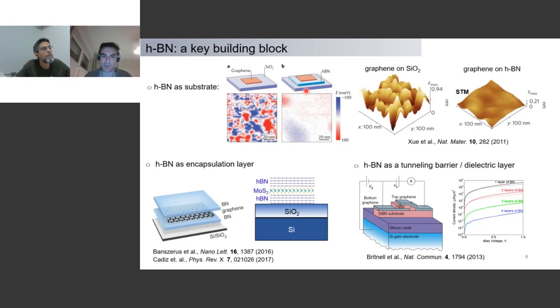And then what was realized is that if you deposit these graphene flakes directly on HBN, which is quite smooth and has a 2D surface, you get a very nice surface potential. It's much smoother than before, and this is reflected in the mobility of graphene on HBN, which is much higher than what you get on silicon dioxide. And you can see here by STM that the quality of the surface improves quite a lot. It's much smoother. So I would say this is the main use of HBN in this type of heterostructures.